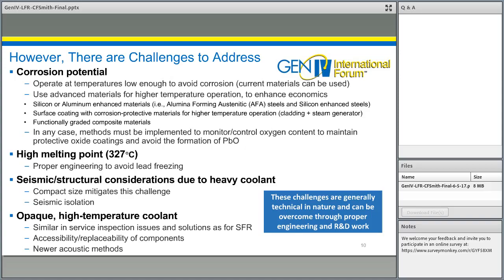Coming back to the issue of corrosion, it's well known that lead and lead alloys are corrosive to conventional steels at high temperatures. Corrosion prevention can be achieved by operating at temperatures low enough to avoid such corrosion phenomena. For this condition, current materials could then be used. The temperature limit for this is generally taken to be about 480 degrees centigrade. A second approach is the use of advanced corrosion-resistant materials for higher temperature operation. New materials such as silicon or aluminum enhanced steels, for example, alumina-forming austenitic steels and silicon-enhanced steels is one approach.